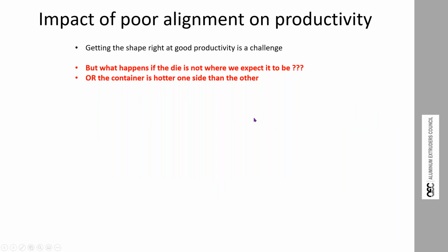Now then, there is an impact of poor alignment on productivity. If we make the wrong shape, it's scrap, right? So what happens if the die isn't where we expect it to be relative to the container? That slow moving metal at the edge of the container, the die designer has taken it into account when they design the die. But if the die isn't where it's supposed to be, now we have a piece of bearing which is supposed to be in a slow area, and a piece of bearing which was designed for a slow area is now in a fast area. The shape goes to hell in a handbasket.